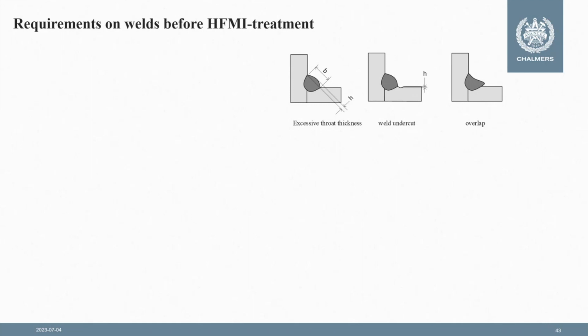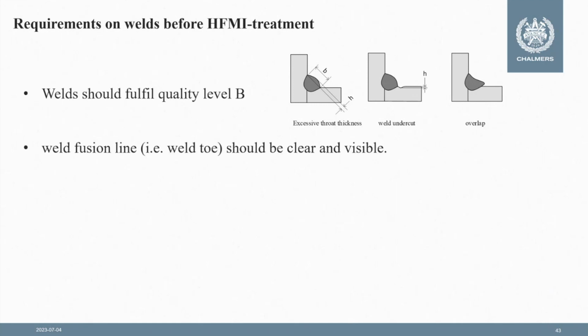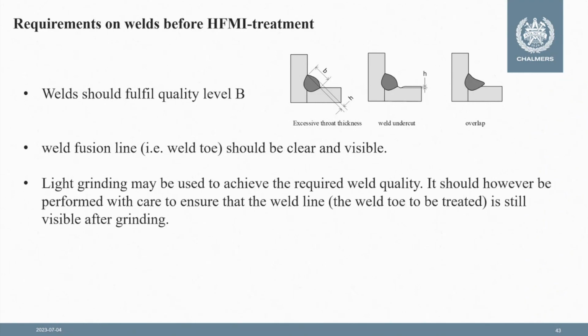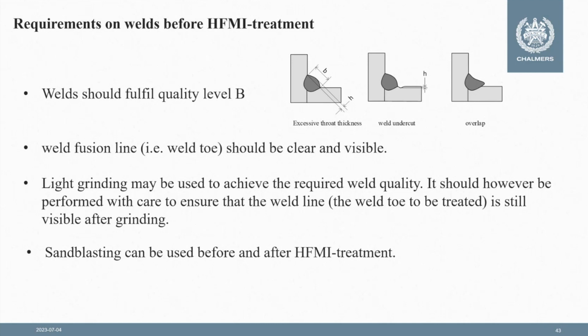In principle, the weld should fulfill quality level B. The fusion line, or the weld toe line, should be clear and visible so that the treatment is placed in the right position. If the weld doesn't fulfill quality B and light grinding needs to be used, for example, to meet the quality B requirement, it can be done, but it should be done in a way that it doesn't erase the weld toe line, so that the operator who will do the HFMI treatment can still trace the weld toe line. Sandblasting, of course, can be used both before and after HFMI treatment.